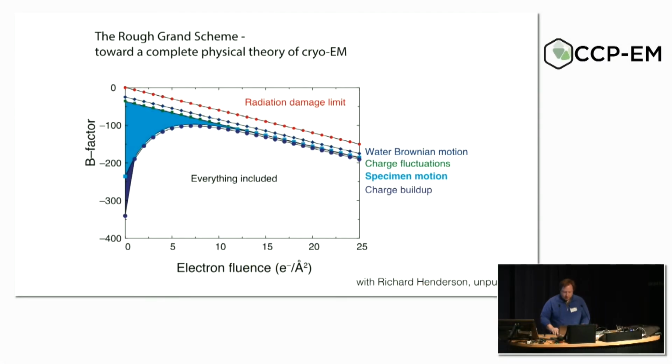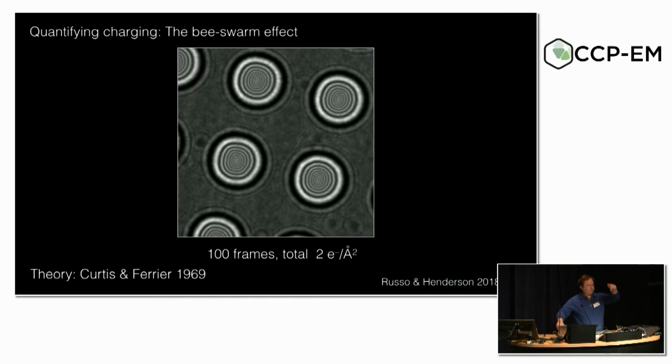So what is this? So the electron comes down on the specimen, very high energy. It can very easily kick out other electrons. And in kicking out those other electrons, it leaves behind positive charge. Ice is an insulator, charge can't just go flying inside. And then in kicking out those other electrons, they can actually land on other regions of the specimen and charge them up. And you get this whole sort of dancing phenomenon of charge that's happening all the time in your images. And you can see this here.